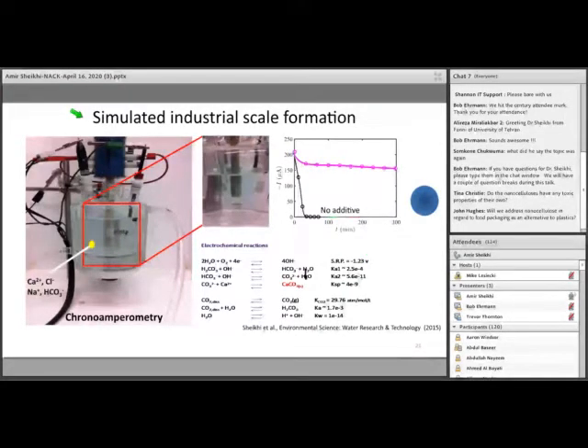How do we simulate the scale formation in the lab? That is definitely a process that may take a couple of months or even years in industry, but the way we do it is through using an electrochemical method called chronoamperometry, in which we fix the voltage exerted on a rotating disc electrode in a saturated solution of calcium and bicarbonate and measure the current versus time. That's why it is called chronoamperometry, measuring current versus time. So if the electrode doesn't scale, the current will look like this. There is no significant change in the current, but as the scale is formed, as you can see here, the current decreases until it reaches zero because the scale is an insulating material.